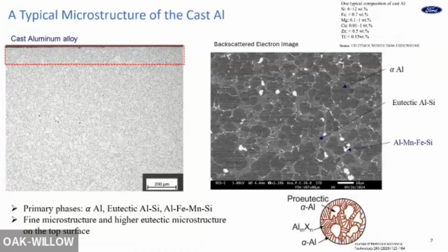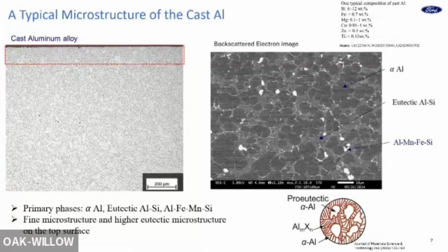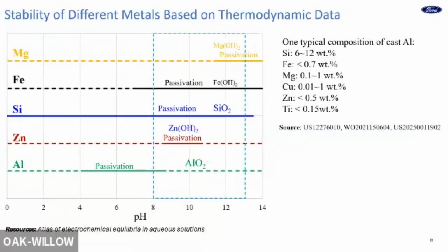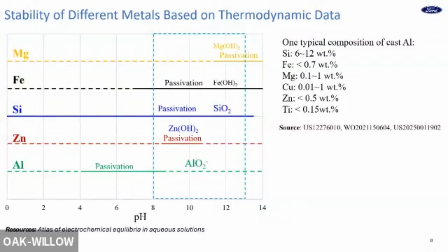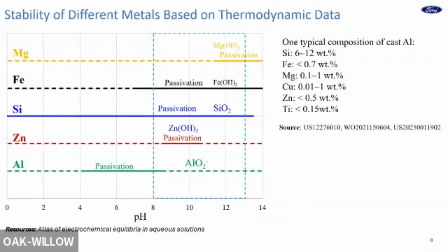So now we know what's happening in the paint shop. We also know the microstructure and the chemistry of the alloy. Then what happens if you dip this alloy into the pre-treatment or cleaning solution? When you look at the commercial products, there can be many different compositions. So here we're just trying to use a simplified metal stability versus pH diagram to get an idea what might happen. This is solely based on thermodynamic data, but it can be very useful to predict the behavior of a new material in a new system when the information is limited.